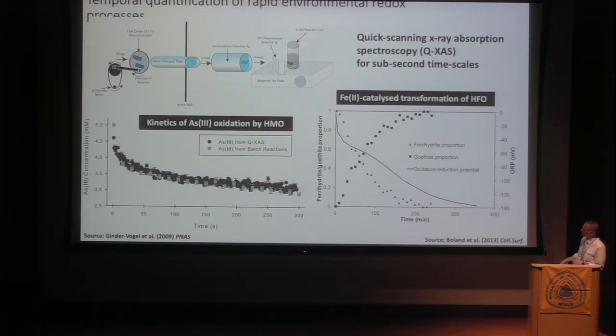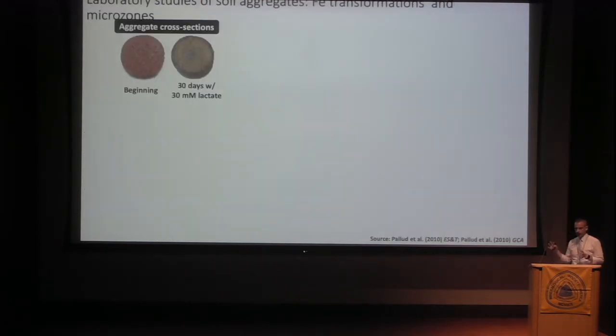But being able to track the change in the mineralogy of this material, again, at the sub-second time scale, and being able to say what's happening in the mineralogy of the system. And again, we're starting to approach our ability to get at the kinetics of geochemical and biogeochemical reactions, whether they're redox reactions or dissolution precipitation reactions. I'm going to start now moving up into first laboratory and then field-based experiments as we're increasing our scale of what we're looking at.